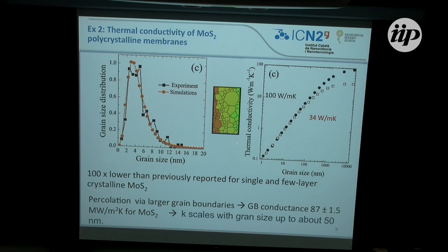But the model allowed us to see the thermal conductivity dependence, or maybe I should talk about thermal conductance, on grain size. Right? So the experiments we had were at 0.7 watt per meter Kelvin. These are the values. I don't remember where these values came from, maybe from a previous slide. But these are the values that depend on the grain size. So we think that it's a percolation-like propagation of phonons. They basically go and scatter off grain boundaries. The conductance is of 87 megawatt per meter square Kelvin, and the conductivity then scales up to a certain size. After that, it begins to deviate quite dramatically.